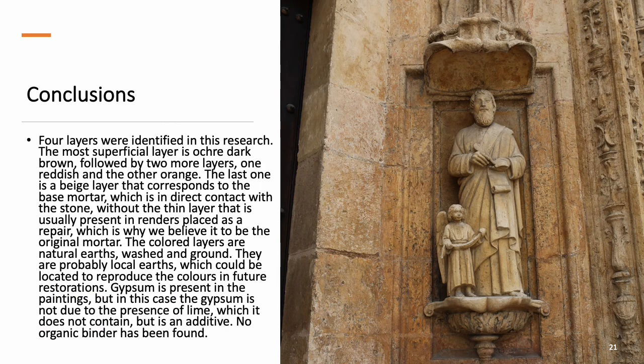In conclusion, 4 layers were identified in this research. The most superficial layer is ochre dark brown, followed by 2 more layers, one reddish and the other orange. The last one is a beige layer that corresponds to the base mortar, which is in direct contact with the stone, without the thin layer that is usually presented in render, placed as a repair, which is why we believe it to be the original mortar. The colored layers are natural earth, washed and ground. They are probably local earth, which could be located to produce the colors in the future restoration.